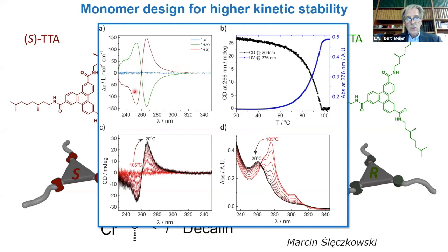Now, if you heat such a sample at a certain temperature, let's say at 100 degrees, then it disassembles and the CD is gone. If you then cool again, the CD spectrum comes back, and the same you could do with UV spectroscopy. At high temperature, you see a molecularly dissolved molecule, and at 20 degrees, it's a supramolecular polymer. What we then typically do is sit on this peak in the circular dichroism spectrum at high temperature, where it is zero, and then we cool very slowly. And here we see the nucleation of the supramolecular polymerization, and then it starts to grow. And here you have the polymer formed. Everything in line with what a lot of people in the world do, and we didn't have any surprises.